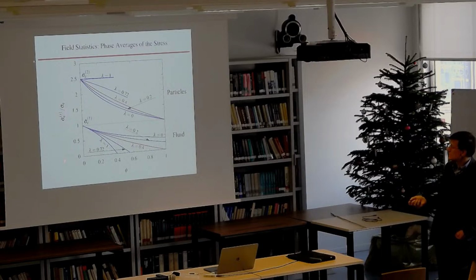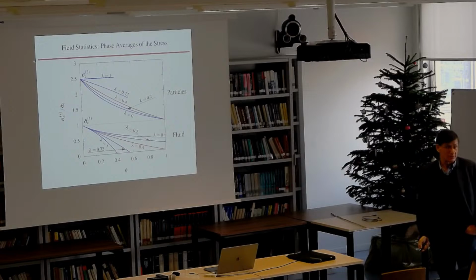The averages of the stresses, for example, as a function of lambda. Here's lambda equals 0.72. So what does it say? It says that the stress in the matrix goes down, the average stress in the matrix goes down, and it goes to 0 actually at the rigidity threshold.